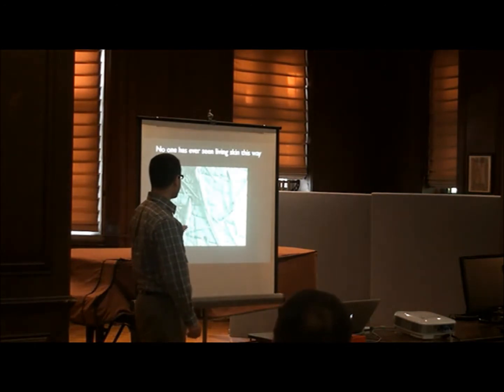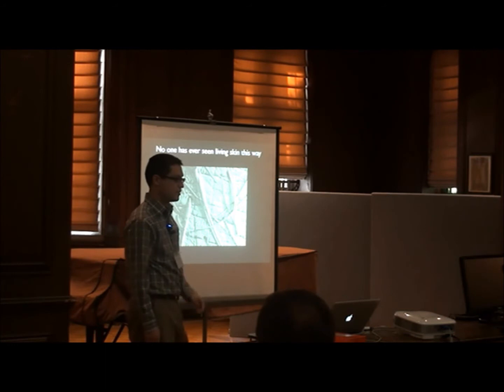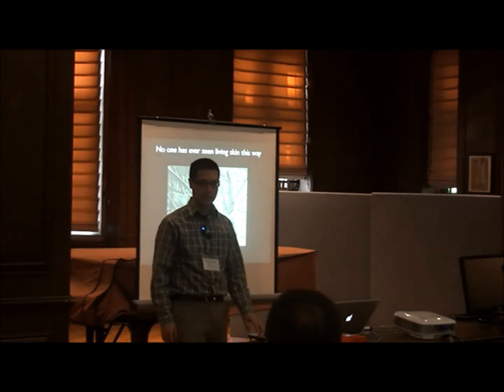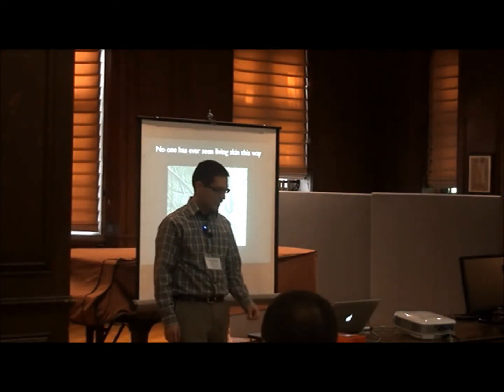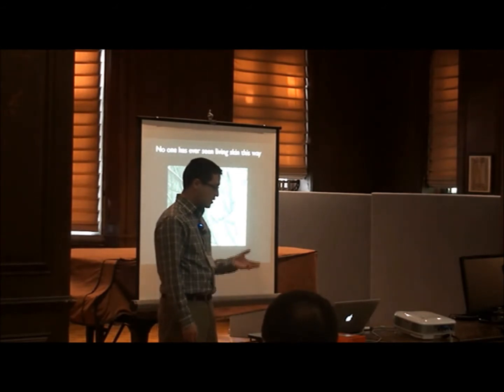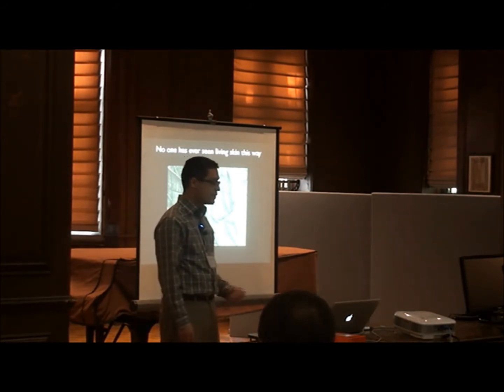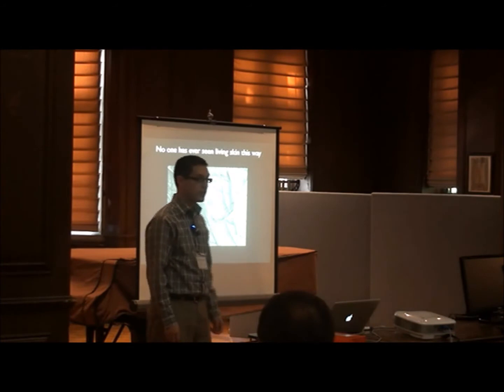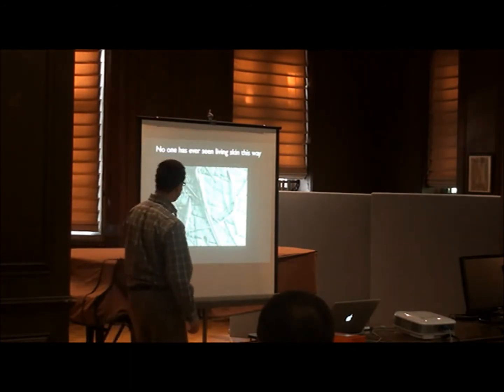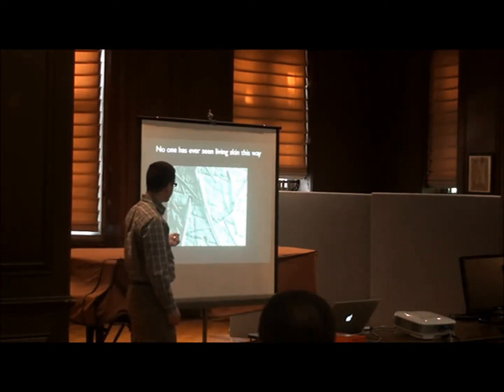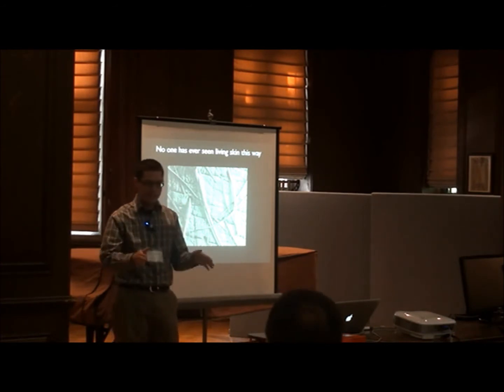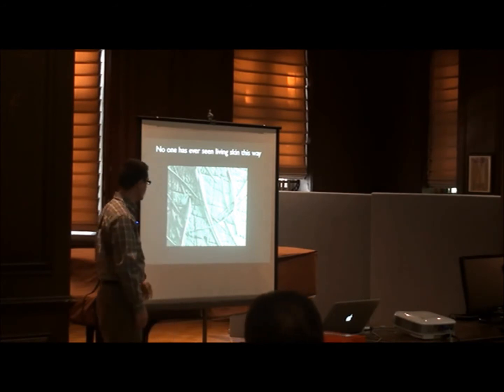And we can get images that no one has ever really seen before. And people at cosmetics companies who do research on skin have validated that we're really seeing features in vivo that are very hard to see. So this is again a striking image because you don't see the gel. You might expect the gel to behave like a tent and flow over, and you'd see some kind of structures, but it really doesn't seem to be there at all.